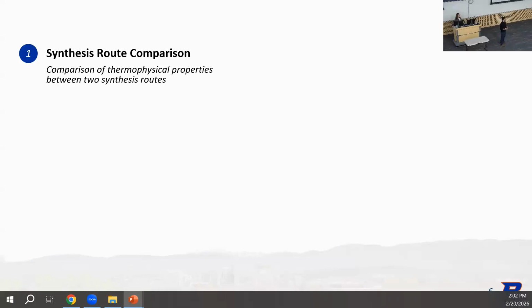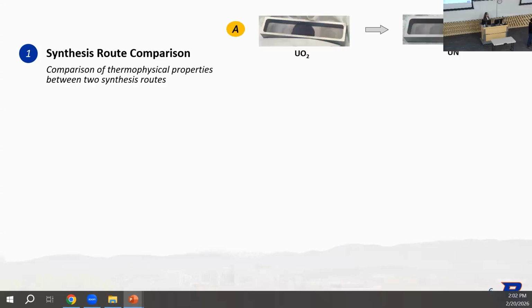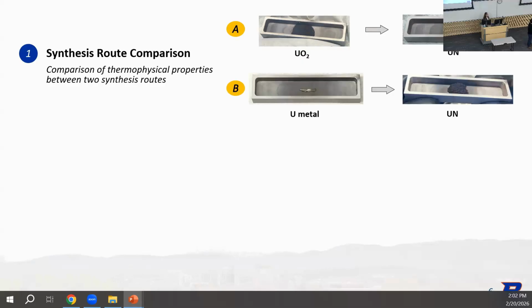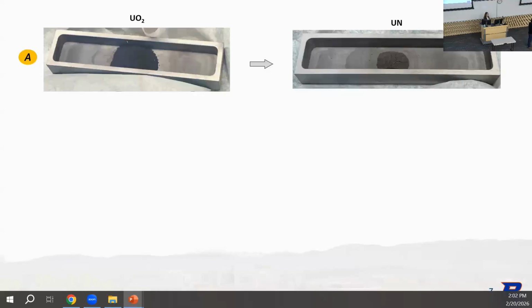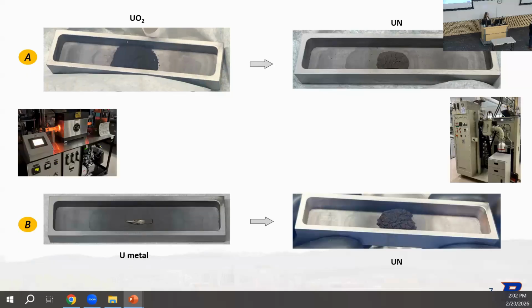The comparison of thermophysical properties and chemical properties between 2 synthesis routes, one which starts with the current feedstock for the fleet, UO2, giving us UN, and then another one that starts with uranium metal, which then also gives us UN. So let's take a quicker look at that. As I said, we have UO2, and we mix this with carbon, and then we put this into a tube furnace, as seen there on the left, and then this produces UN, which then we can take that powder and form those nuclear fuel pellets in the furnace on the right.